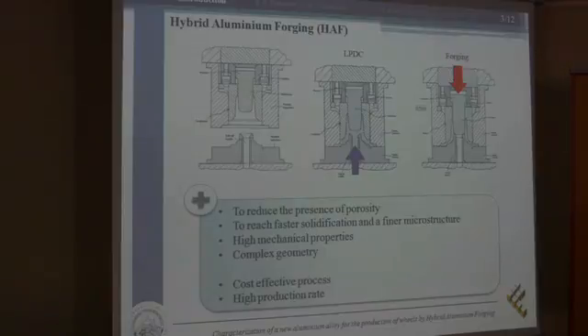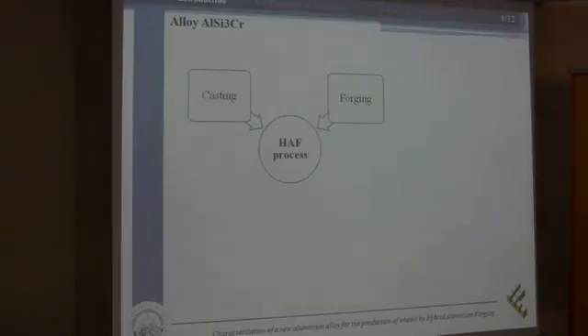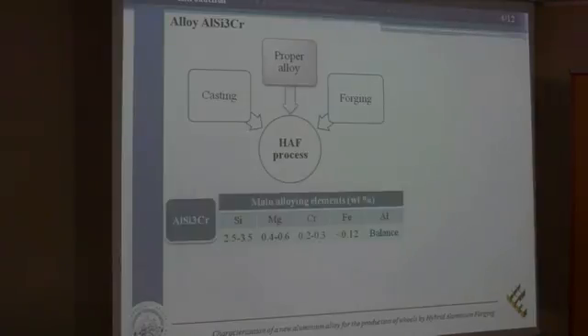At the same time, it is still possible to have wheels with a complex geometric shape, and also another important characteristic is the possibility to have a process which is cost-effective and which can ensure a high production rate. But it is not possible to achieve these goals by just combining these techniques. Indeed, it is fundamental to use the most suitable material. The alloy under study, which is used at pilot plant scale, is an alloy containing silicon, magnesium, and chromium addition with the content shown in the table.